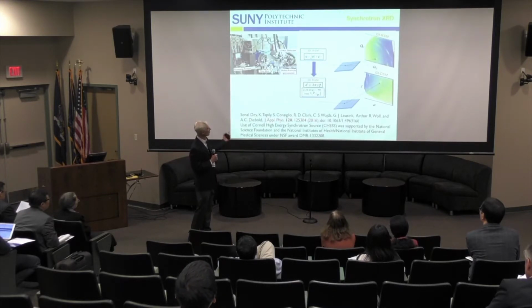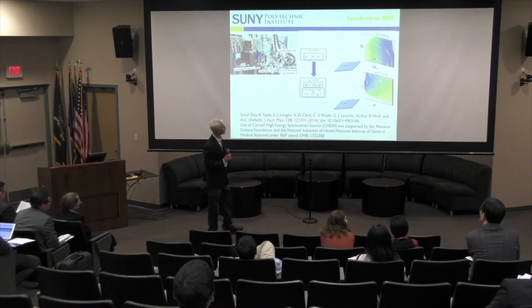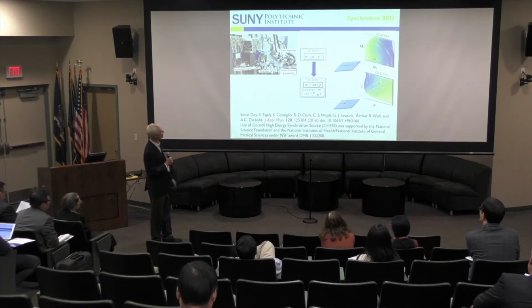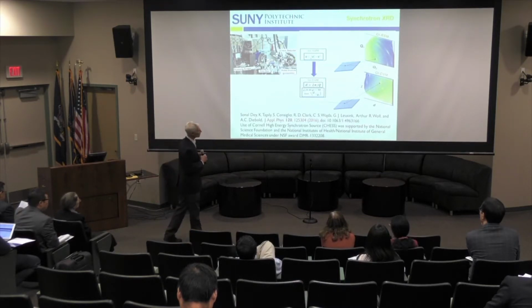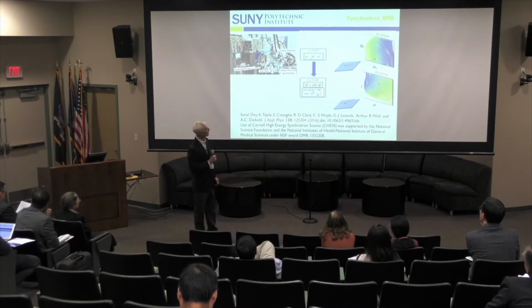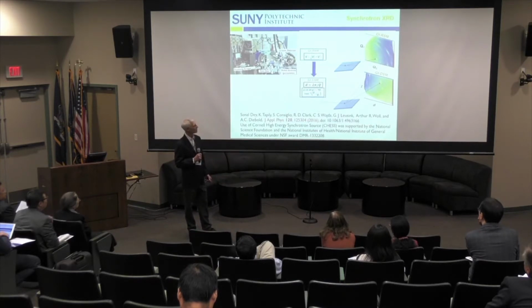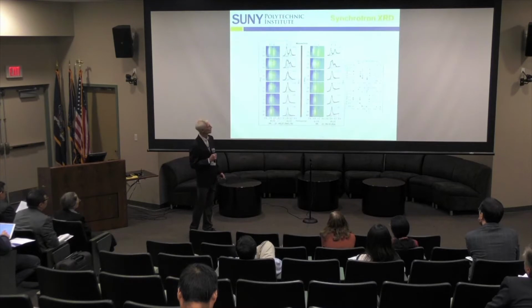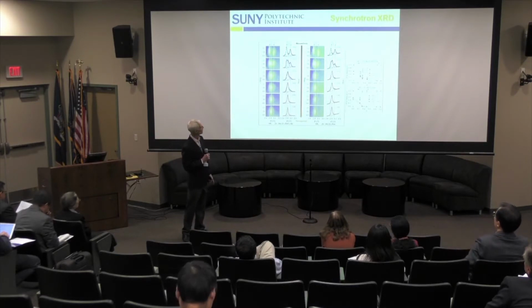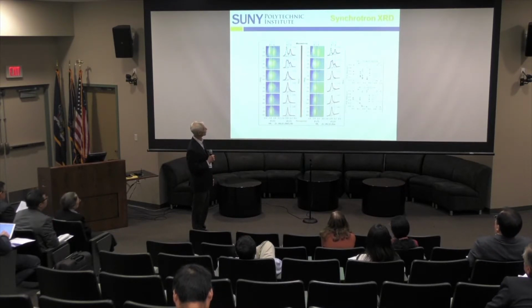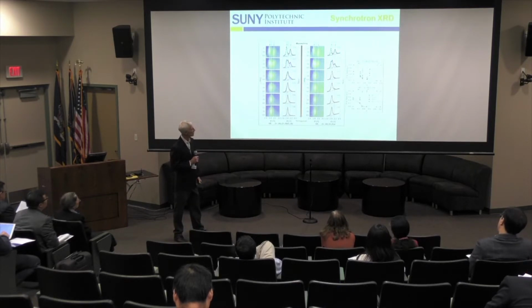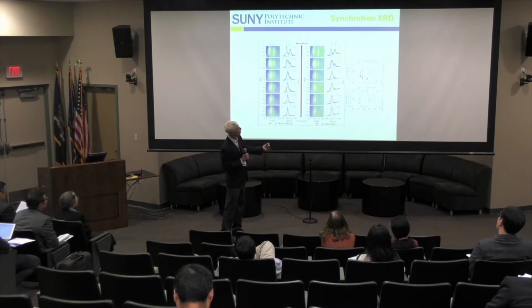And as I said before, we've done a lot of work in the group here, and Steve right here is in the audience, smiling, I think. And this is the X-ray diffraction work, grazing incidence X-ray diffraction, synchrotron-based. It's been done at Brookhaven as well as at the CHESS facility at Cornell. And this is how hard it is to get X-ray diffraction phase information about some of these very thin films. And here's an example of how we were able to follow from monoclinic to tetragonal for hafnium zirconium oxide with different compositions. We were able to monitor from the X-ray diffraction data what phase it is and see when it's changing between one and the other.